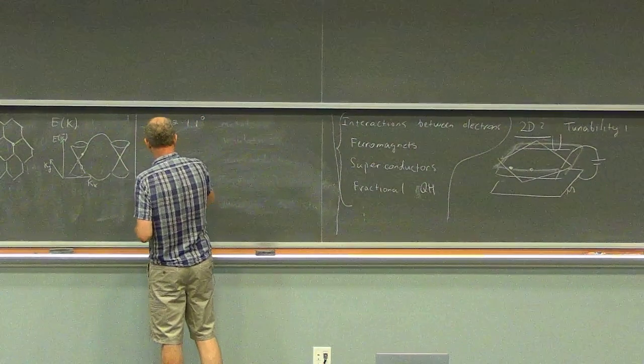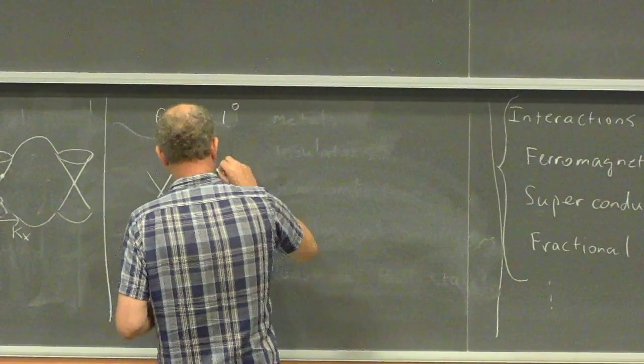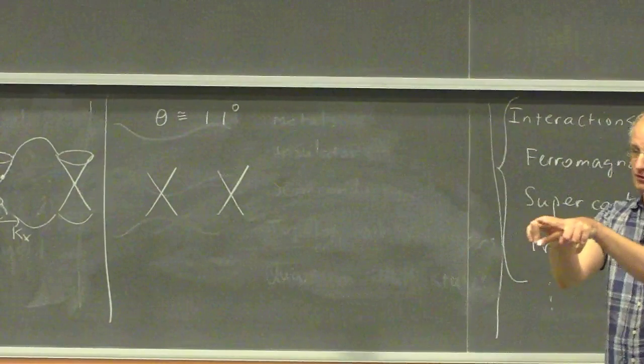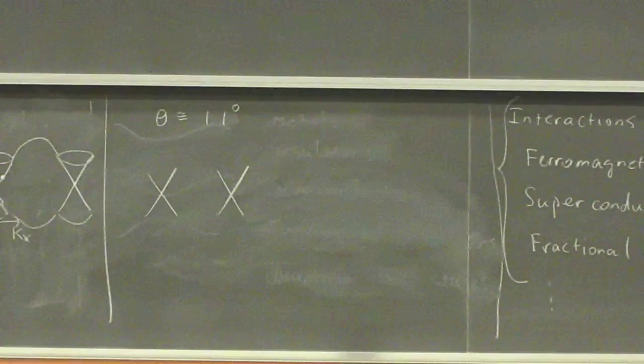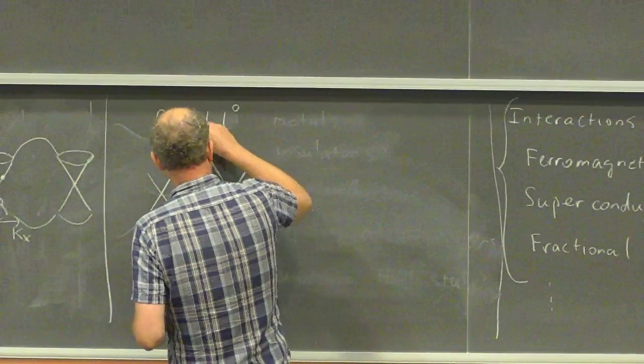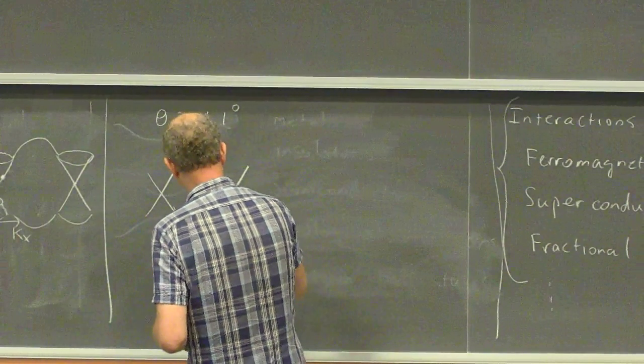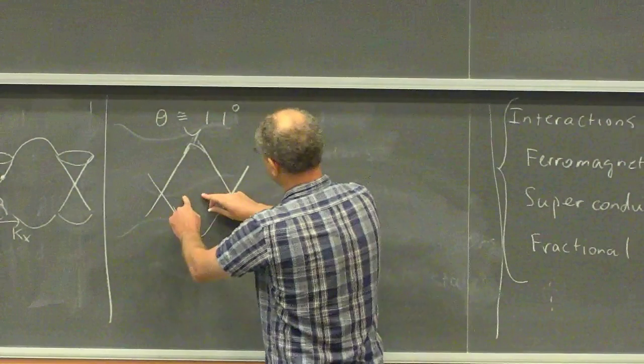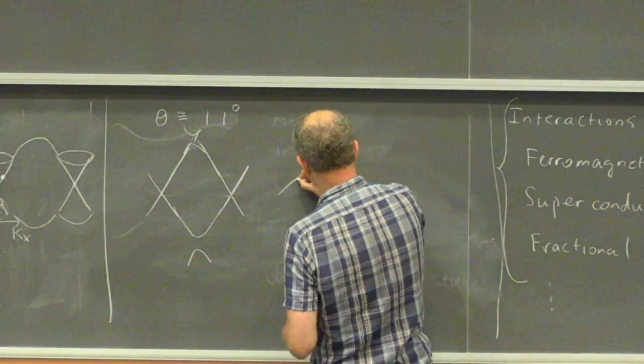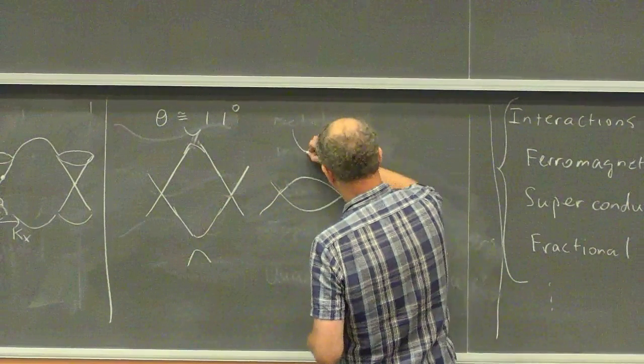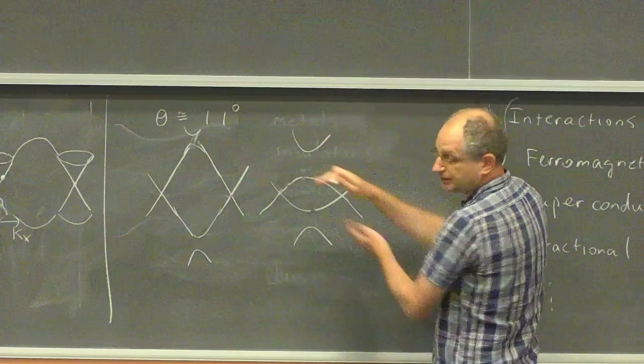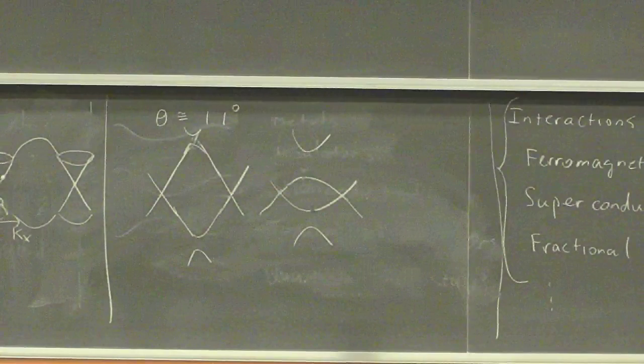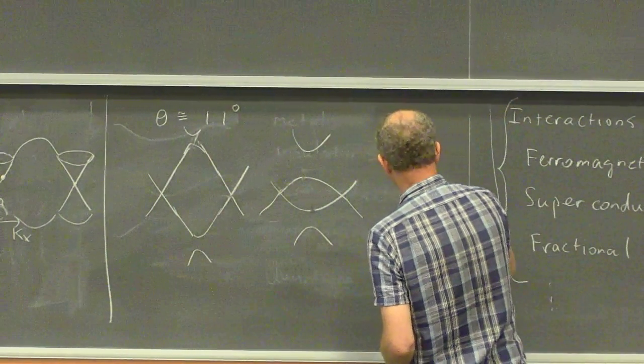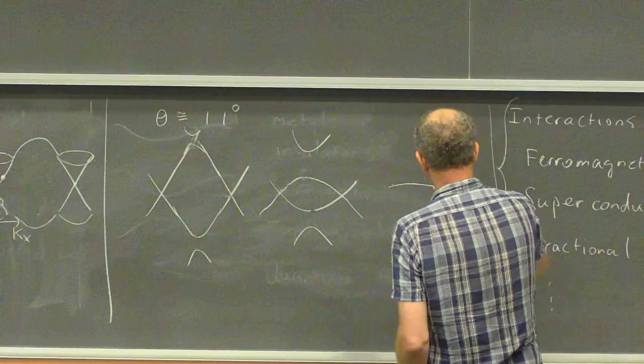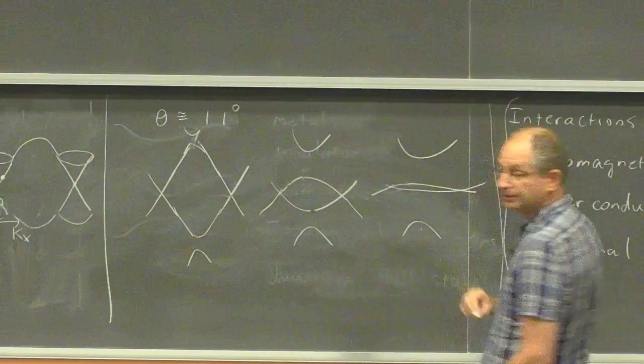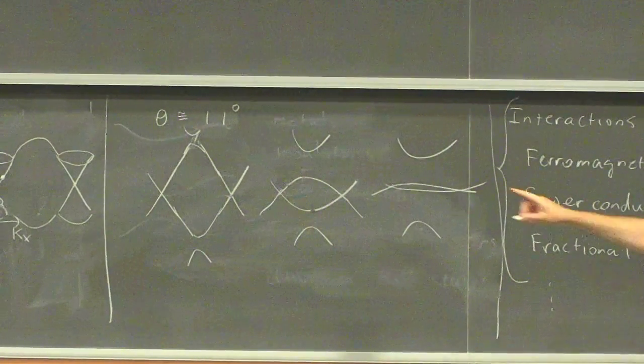So what actually happens as you do this? You start from the Dirac dispersion of the two individual layers that are slightly displaced in momentum space because of the small angle. Then they hybridize with each other. There's some avoided crossing here, and so on. As you make them closer together, this point becomes lower and lower in energy. And if you think it through, this dispersion would become narrower and narrower in energy as you make these 2 points close. The prediction was there's going to be some angle, this angle, where you're going to get almost completely flat dispersion.